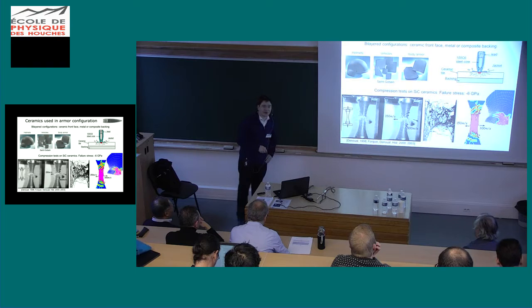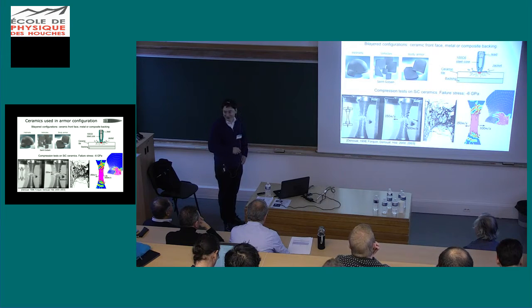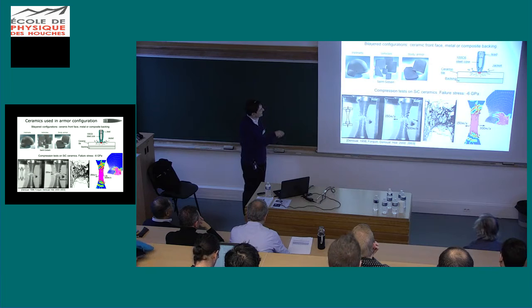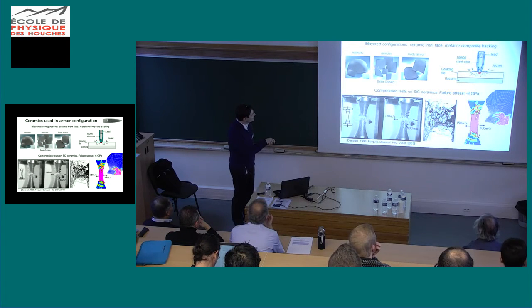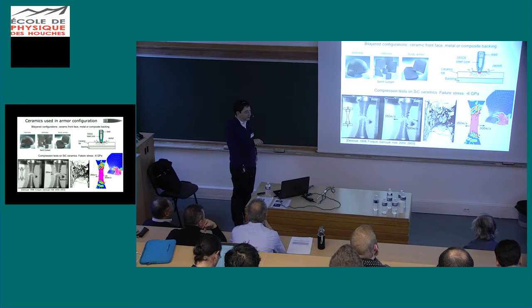I was in a master, it was my master project, so it was quite a long time ago. And you can see the very nice experiment we performed with Christophe Denoil. It consists in compressing in quasi-static, so the loading is a few minutes long, a sample that is a Diabolo sample, as you can see. And we can reach up to 6 gigapascal of actual stress in this part of the sample, the ligament of the sample. But what happened in a few microseconds is a brittle failure.